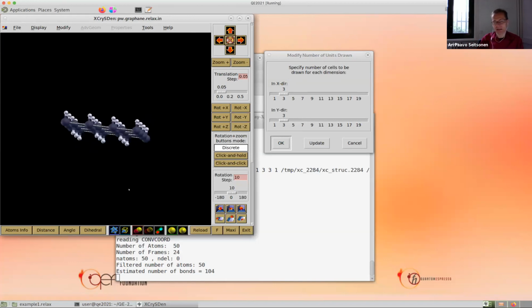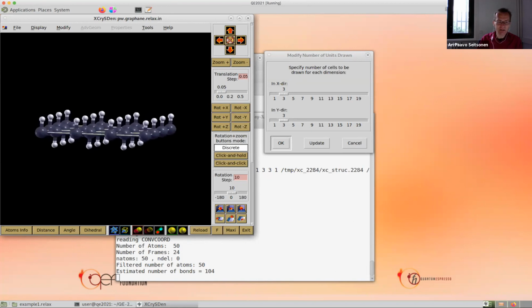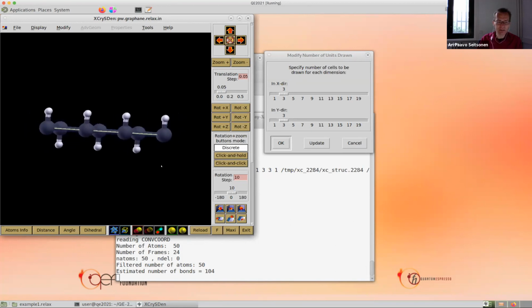And it is quite easy to understand that it's energetically preferable to put the 2 atoms alternatively. So you put every second atom above, every second below this plane of the atoms. So we start from the flat plane of graphene, and then we will see what happens. This will be the target to optimize the structure in this exercise.